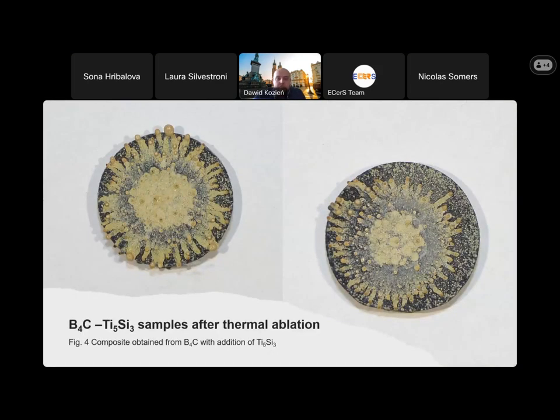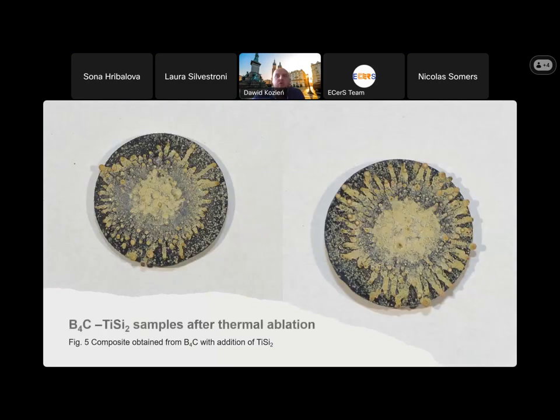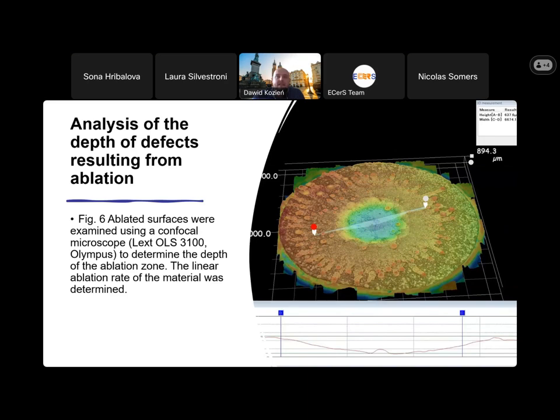After, when you use intermetallic additives, titanium silicide, Ti5Si3, we can see that the structure was a little bit changed, and we have a problem. It was not so good. The same with titanium disilicide. But of course, we analyze everything, the surface, how it's influenced.